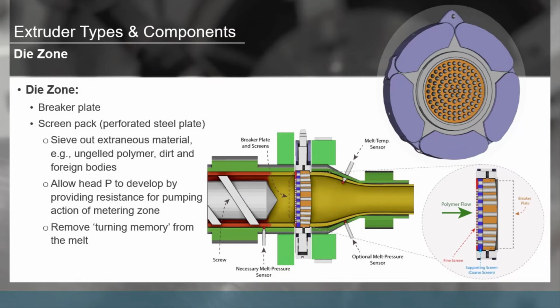And the screen pack is primarily made out of perforated steel plate. It sieves out extraneous material, for example, any kind of ungelled polymer or dirt or any kind of foreign bodies. It also helps to remove turning memory from the melt. And then it also allows head pressure to be developed by providing resistance for the pumping action of the metering zone. That way you have a high pressure zone, and then outside you have a low pressure. So obviously there is a transition of the material from the high pressure to the low pressure.